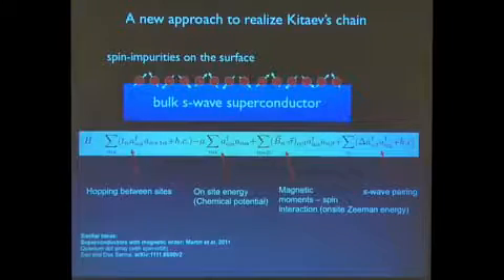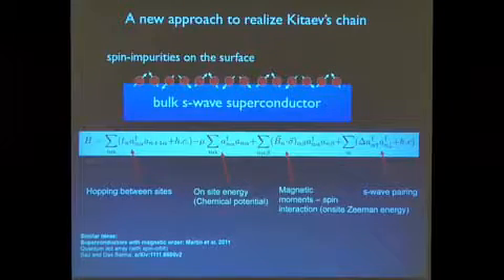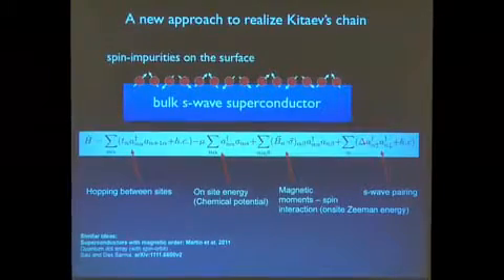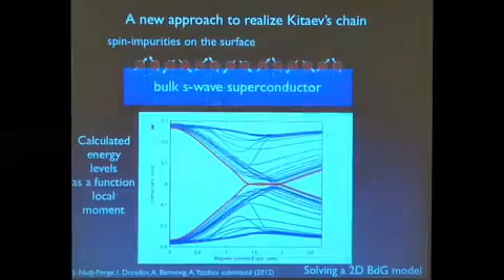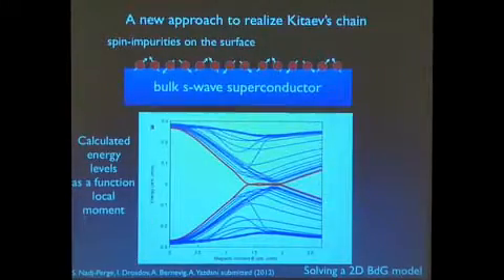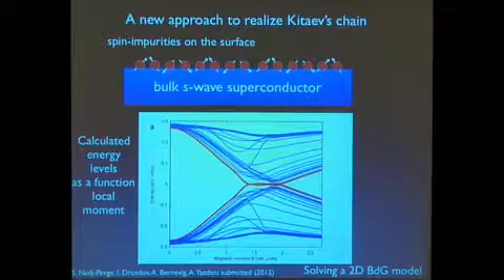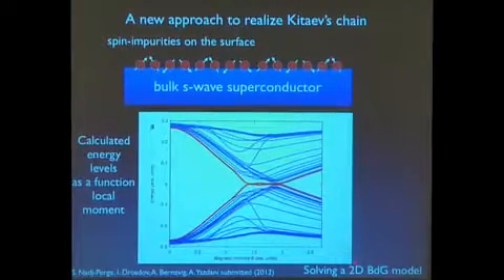Okay, so what does this have to do with Majoranas? We built a chain of these impurities. What you have in this chain idea is the ability for the electrons to hop from impurity to impurity. That's this term. You have some local exchange interaction, which I just told you about. And of course, you have superconductivity, which is being proximitized, if you like, onto that wire. Now, this is where you turn the crank and calculate the electronic states of this system on a lattice of, say, 40 by 40 atoms. You solve what's called the Bogoliubov-de Gennes equation.